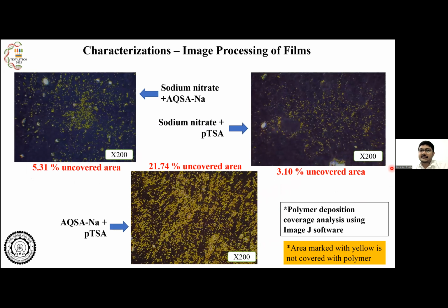Next, image analysis was done, and polymerization was performed over a stainless steel electrode, and surface coverage was checked using this image analysis. We can see that in case of the sodium nitrate PTSA combination, almost 97% of the area of the electrode was fully covered, and about 3% of the area was uncovered, where the polymer did not deposit. This is again beneficial, because in case of textiles, we need full area coverage so that the polymer completely encloses the fibers and the yarns for higher conductivity.